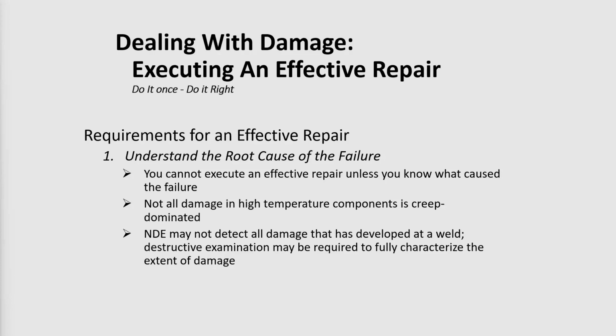And in those cases, and when there's any question at all, then it really is essential to do destructive examination so that there's a good understanding of exactly how extensive the damage is. Because if you leave damaged material in, it's very likely that there'll be rapid recracking in the areas that were not removed, and so the repair in that case will not be as successful as it should have been.